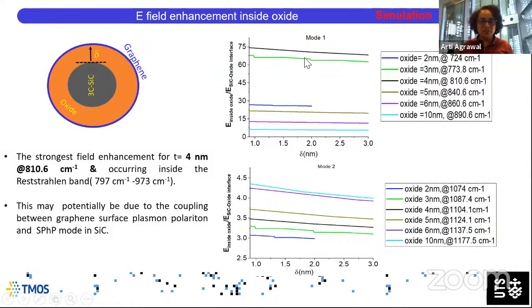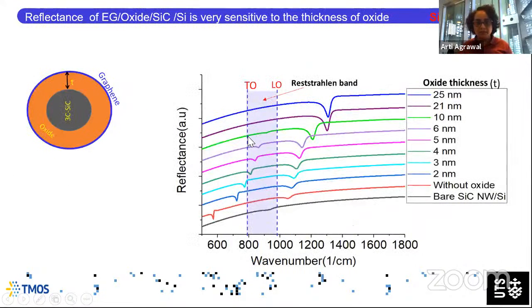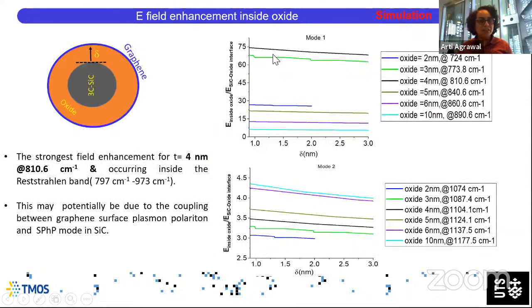All right, so for the first feature, which is formed because of the coupling between the phonon and the plasmon, if we take a ratio of the electric field inside the oxide layer divided by the electric field at this interface, we find that the field is enhanced by a factor of almost 75 at the very maximum for an oxide thickness of 2 nanometers. It is about 60 or so for an oxide thickness of 3 nanometers. As the oxide thickness increases, the coupling decreases and hence the field enhancement decreases. But a 60 to 70 times field enhancement shows you how powerful subdiffraction confinement is for enhancing the field.